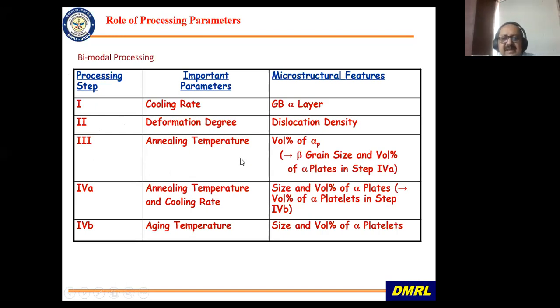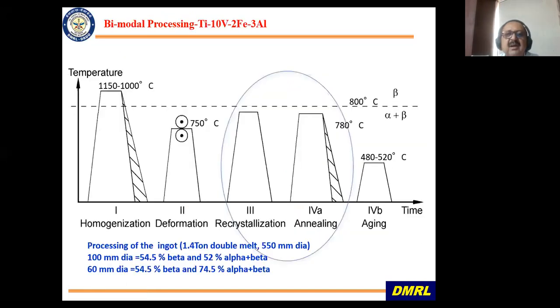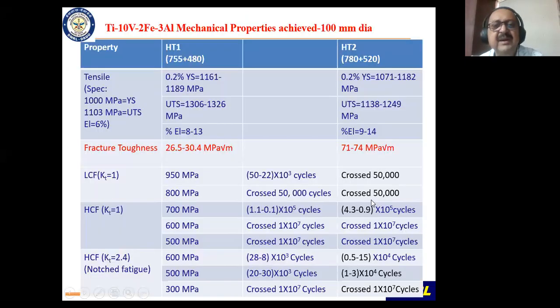These are what the effect of each treatment is. I will not go into this much of detail, but if you want to discuss, we can do that later on. And this is how Ti-1023 was processed. It was homogenized in this temperature range, then alpha plus beta deform, and then it was annealed at 780, and then aged around 480 to 520 degrees centigrade.